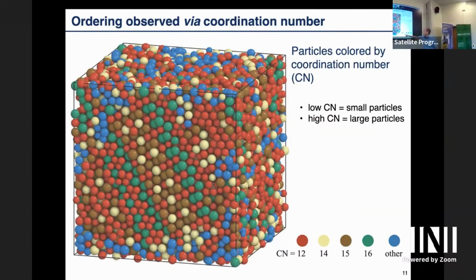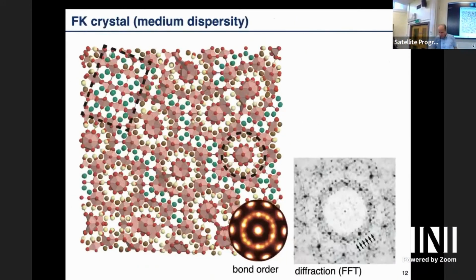And what you do here is you color the particles by coordination number. So you have 12, 14, 15, 16. This is what people who know about Frank-Kasper phases recognize. These are the Frank-Kasper coordination numbers. There are also others, but the majority here are Frank-Kasper neighbors. So it's like a Frank-Kasper phase. There's still a lot of disorder in there, but there's some crystallization to a Frank-Kasper phase. And you can now clearly see some kind of ordering. Here's some layering, there's something green. So now you see there's order, which was much harder to see before, and you can start analyzing this order.